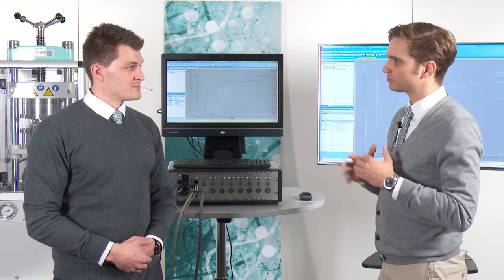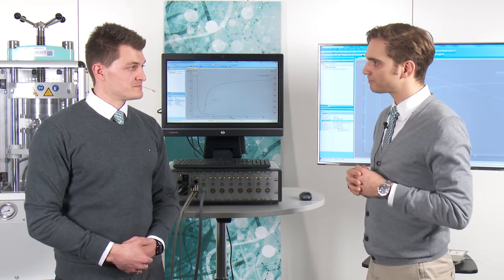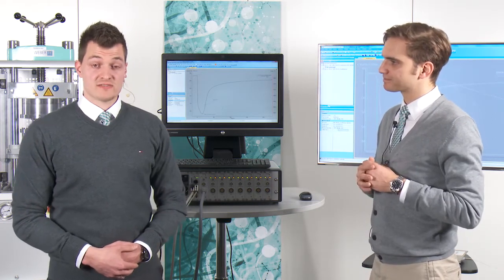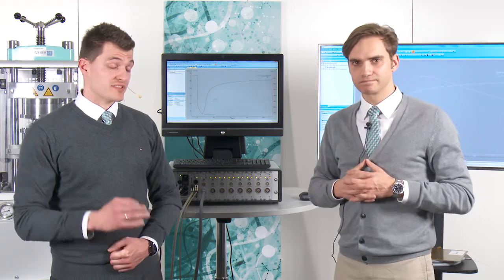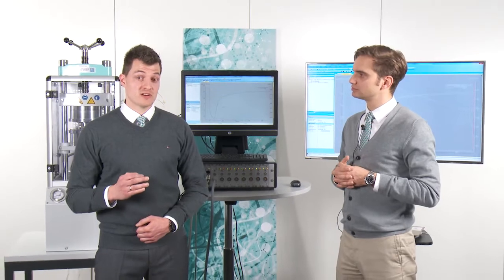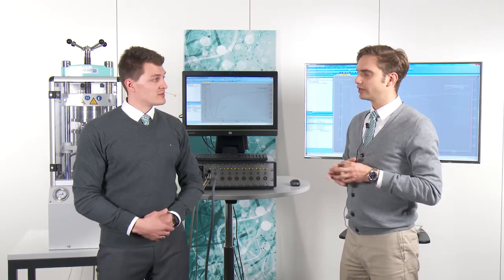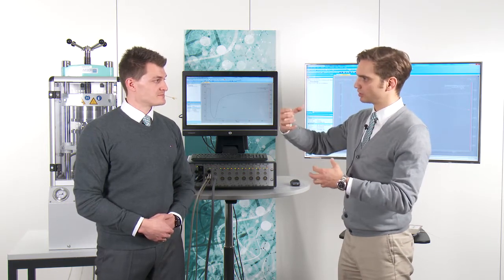One more, UV curing. Can I also do UV curing, because everyone wants to get faster? Yeah, the DEA 288 is a very fast dielectric analyzer, so we have a data acquisition rate smaller than 5 milliseconds. So we can also follow the curing behavior of ultraviolet materials. Okay, and just for you to know, you can also get a lab furnace that has a setup for a UV lamp, so you can get this in a full package for evaluation in your laboratory, for example.